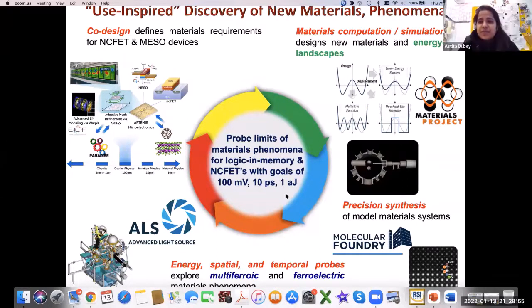Because the d5 electronic structure is actually very stable, even if you excite carriers, they immediately get trapped. The mean free path is like a couple of unit cells. So you don't get very large amounts of current, although you can get very large open circuit voltages.